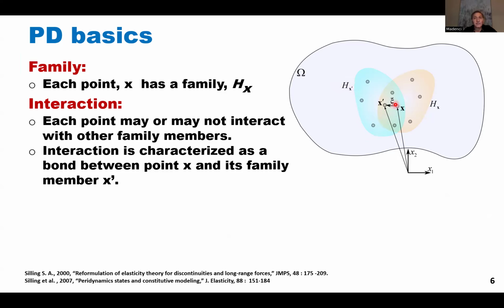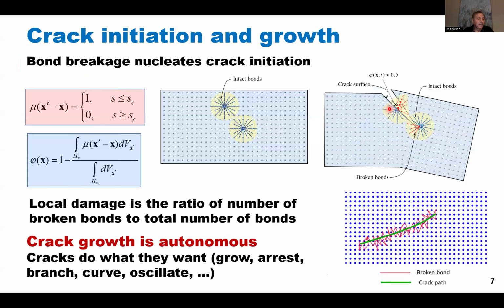And as I mentioned before, this interaction may or may not exist. So if you have crack initiation, you basically terminate this interaction. If there is no crack or it's a continuous field, then this interaction is intact. So originally, Stewart-Silling introduced peridynamic theory to look at material failure. Okay? And by breaking a peridynamic bond, so here's this particular point X, it's interacting with the other points, and the peridynamic bond can be broken.